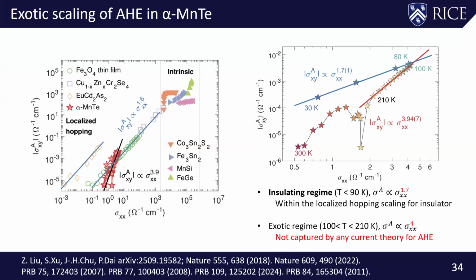So this additional data shows what sort of regime we're seeing in terms of this anomalous Hall effect, as compared with all the other known systems which exhibit anomalous Hall, for example iron germanium, manganese 3, manganese tin, iron 3 tin 2, and all these systems. And the system we're actually seeing is basically in what we typically call the hopping regime, except with an exponent that's actually very strange. It's not really understood.